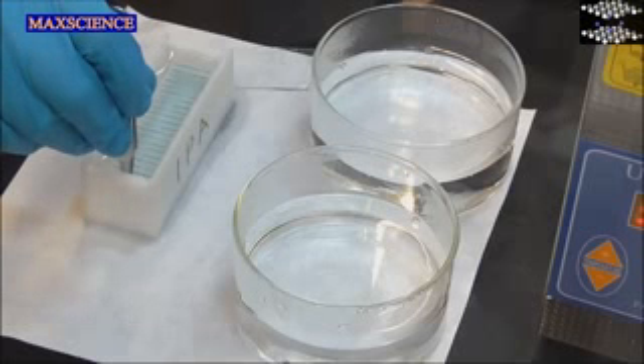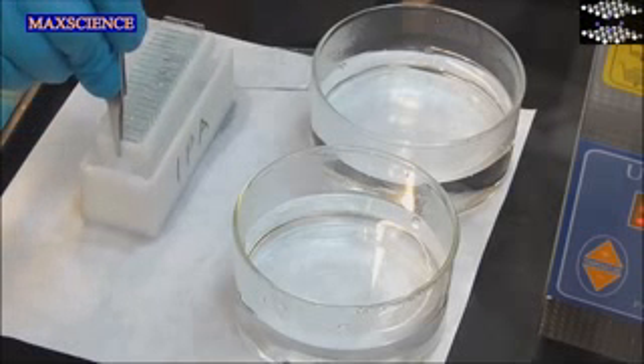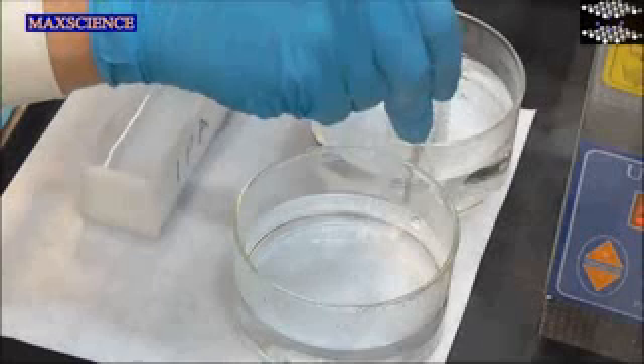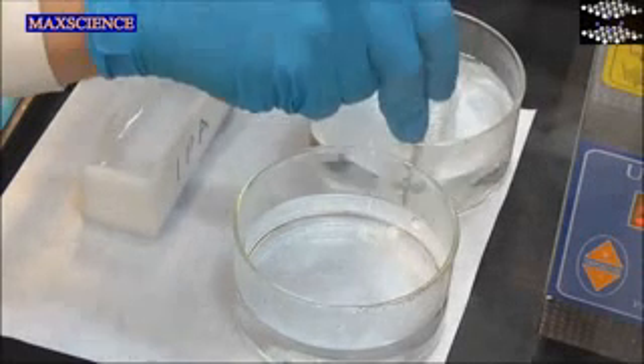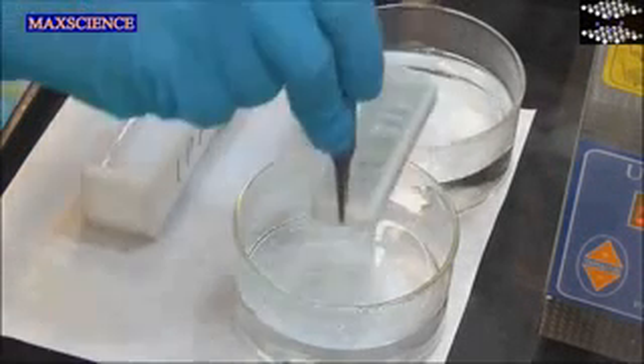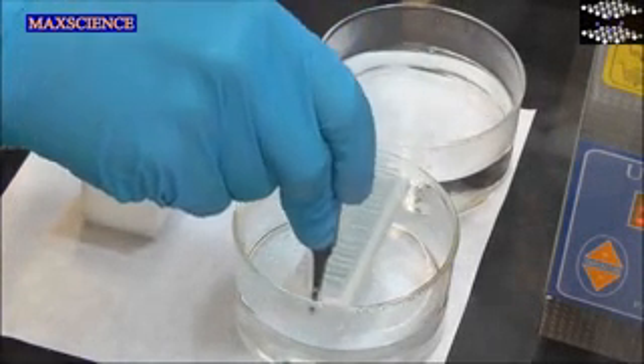The substrates should again be dump rinsed in fresh, boiling DI water. Perform the dump rinse twice to remove all the IPA solution from the substrates.